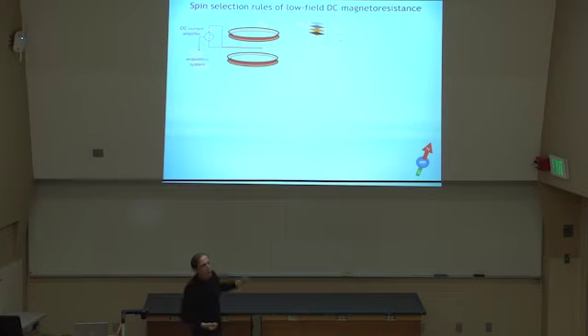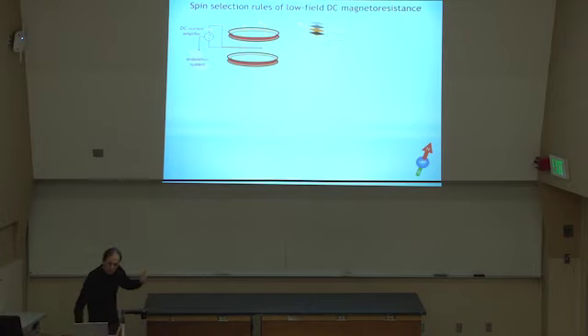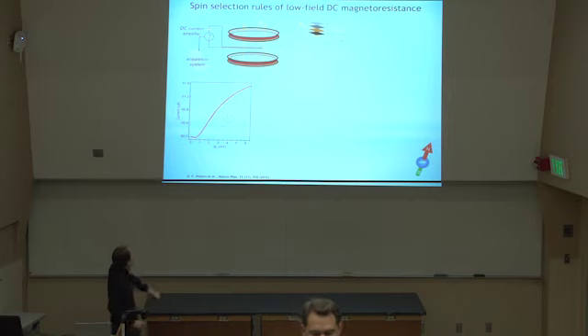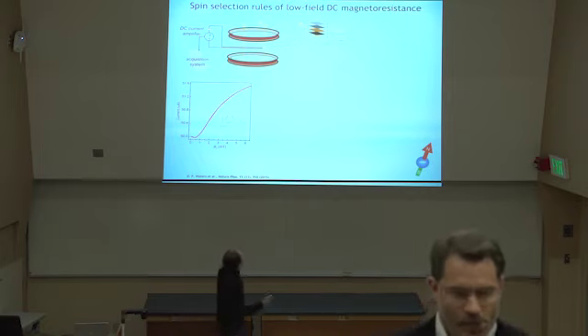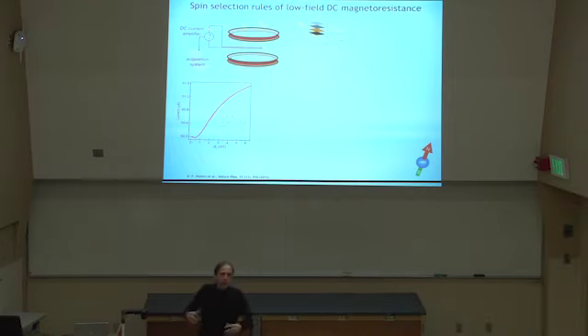The whole point is you can apply a bias, you have charge carriers, and because you apply a bias, you will have a current. And then if you let it sit, then you have a constant current. Let's say you have a device where you apply 50 microamps, and now you change your magnetic field. In other words, you carry out a magnetoresistance measurement.